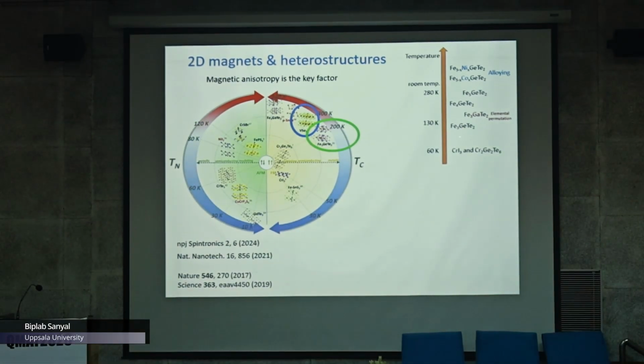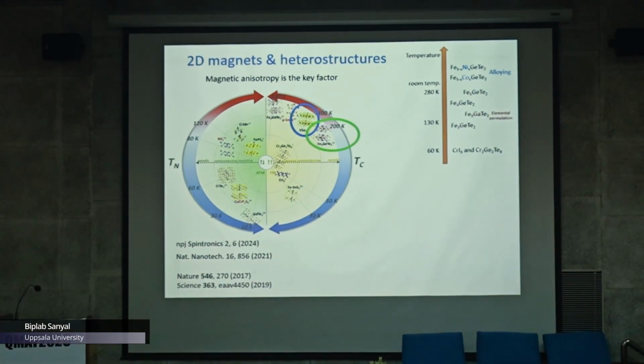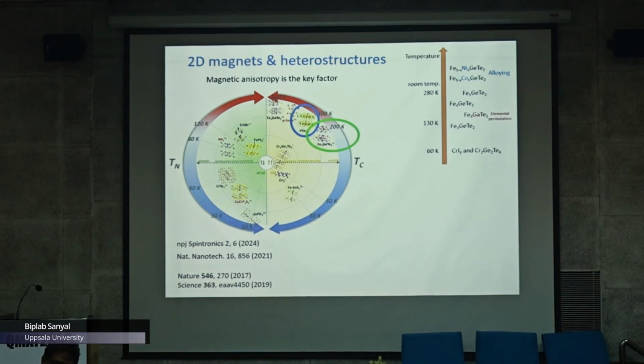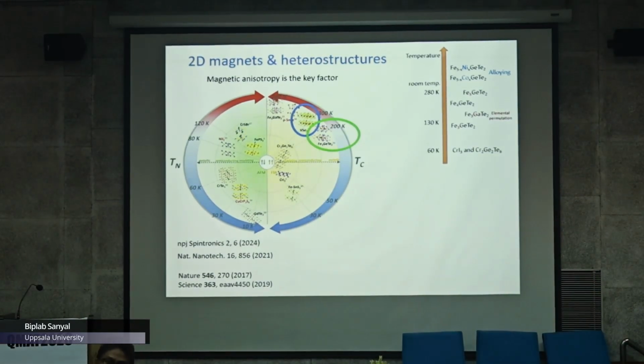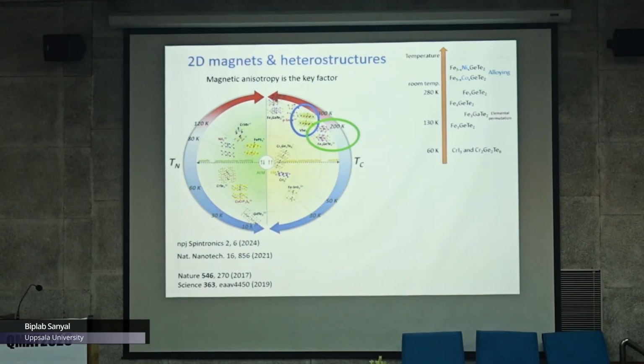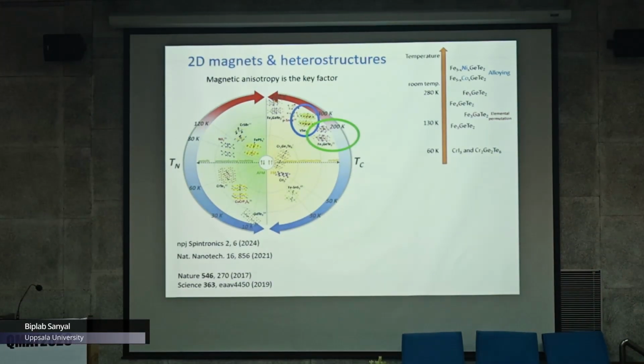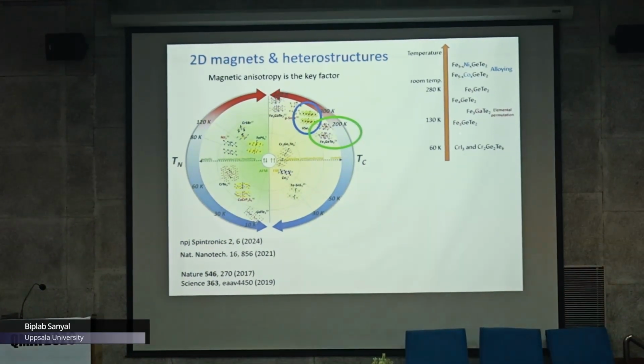Traditionally, the first one to be discovered was chromium iodide, CrI3, which is a ferromagnetic insulator. Unfortunately, the Curie temperature is pretty low in the monolayer regime. It is around 45 Kelvin in the monolayer and 60 Kelvin in bulk. Nevertheless, it shows very interesting physics. And then started